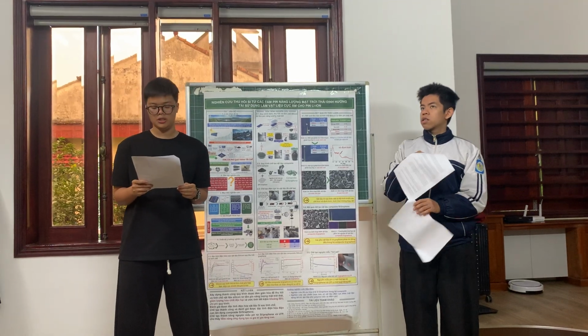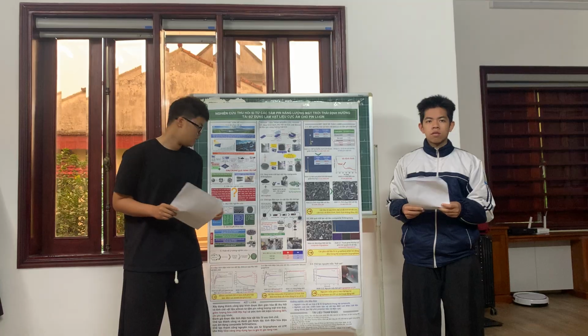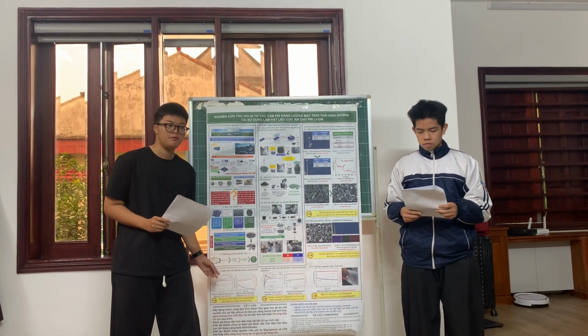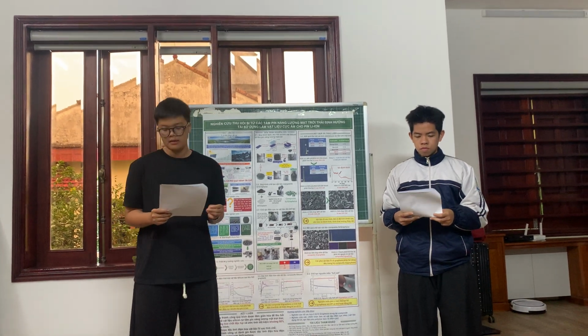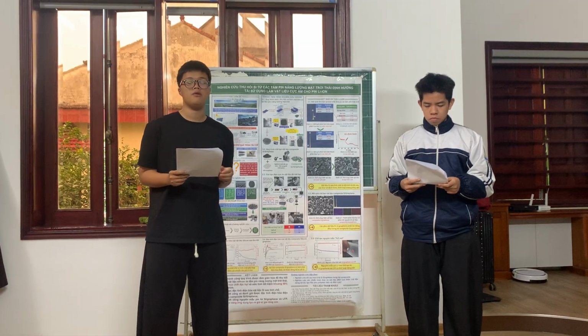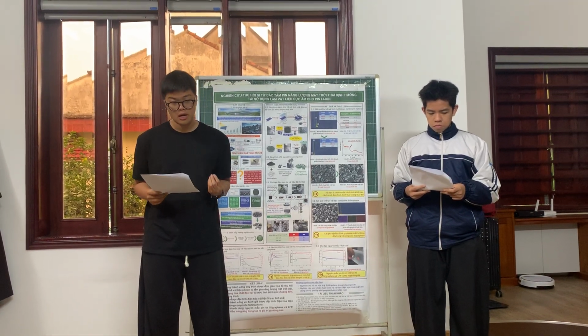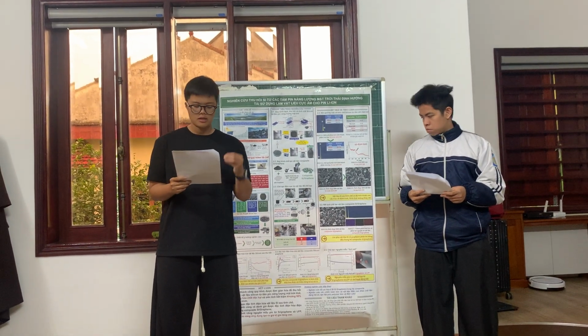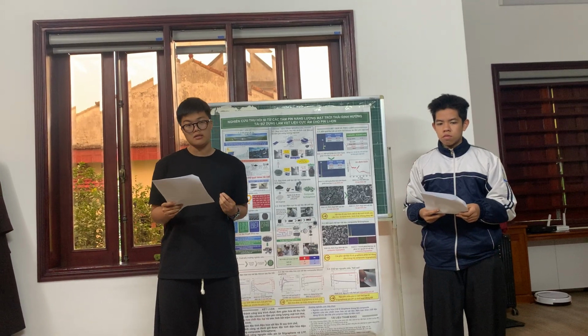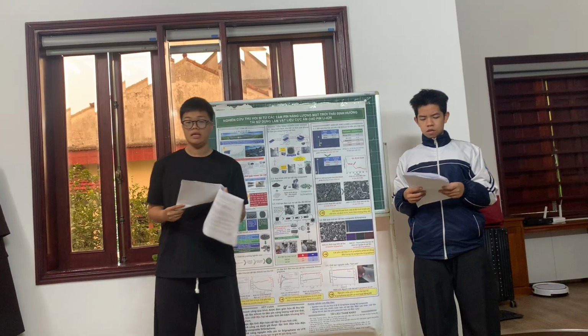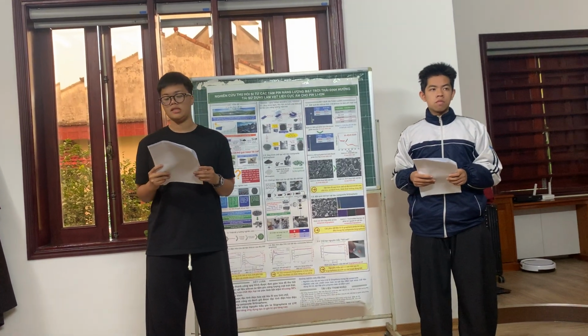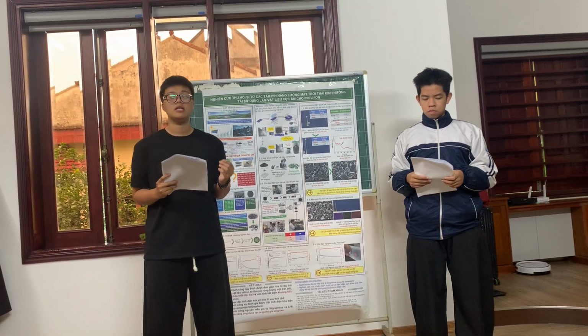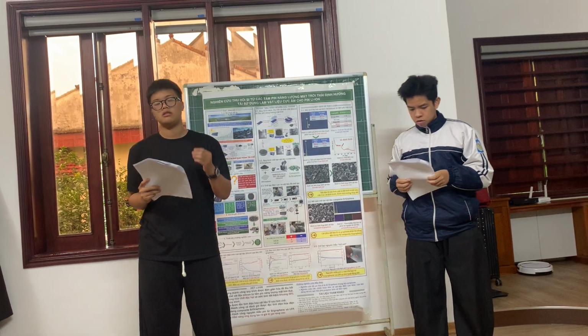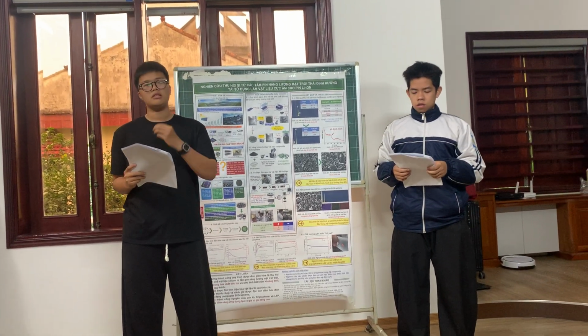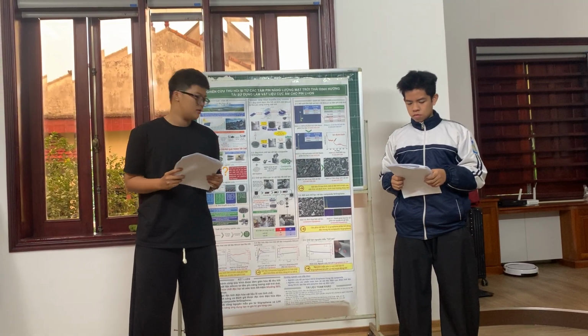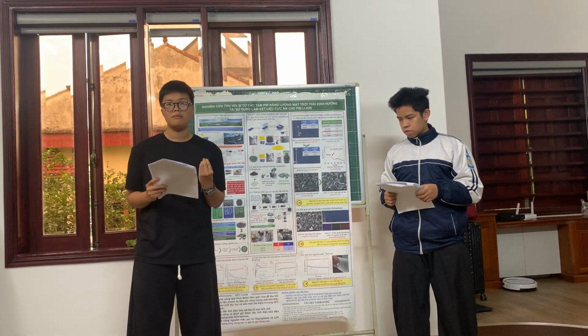To overcome the limitation, the silicon-graphene composite was evaluated. CV measurements show oxidation and reduction peaks similar to those of silicon. The composite has a specific capacity of around 600 mAh per gram and shows stable performance over 100 cycles, demonstrating a significant improvement in stability compared to silicon. Subsequently, a full cell was assembled using this composite anode and LFP cathode. Charging and discharging at 0.5 C show stable performance over 50 cycles. The battery can also power a common LED, highlighting its practical application potential.